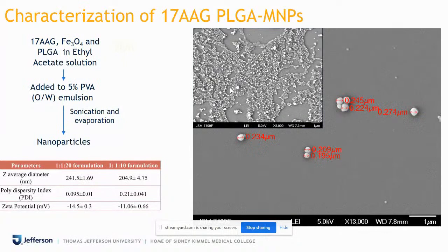So now I'll be talking more about the characterizations of the 17-AAG in magnetic hyperthermia. As you see on the screen, I have provided a short schematic of the synthesis, where we used oil in water emulsion technique, sonication and simple evaporation to create nanoparticles. Although it looks simple, the optimizations and creation of these nanoparticles took a lot of time and effort. But this is the simplest way that I can explain to you in this short period of time.